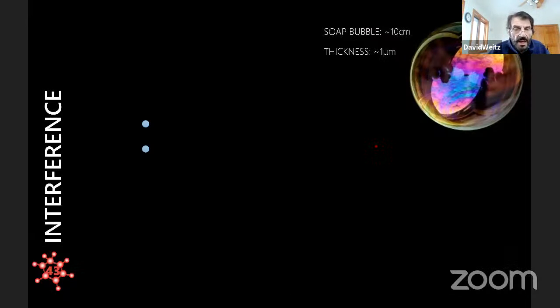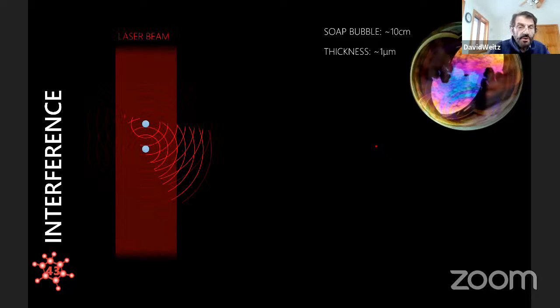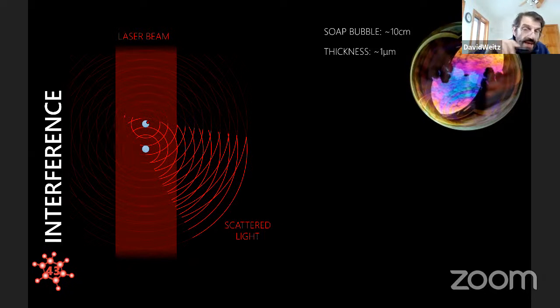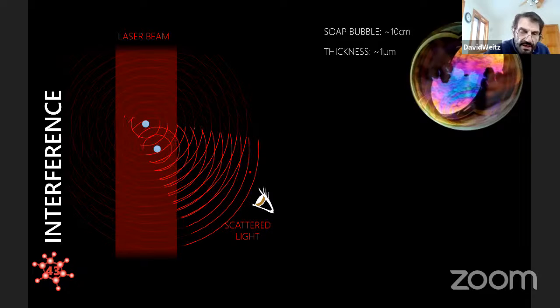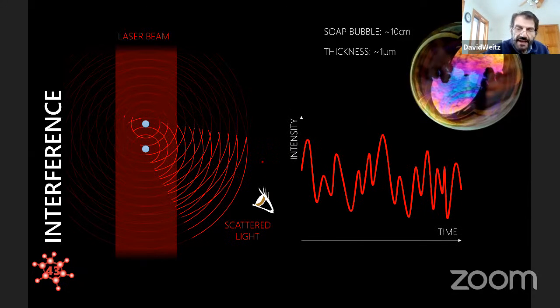So how does this work? Basically you take advantage of interference. You go back to the light scattering of the sample, go back to the speckles. If you have 2 particles, you can image them and try to understand where they are, but a much more sensitive way that people have used for years and years is to take the scattered light and interfere it, and look at the interference of the light. Then when one particle moves with respect to the other, the interference pattern changes. If you just measure the intensity here, you can see that it's changing, and it fluctuates in time. These are the fluctuations of the speckles themselves.